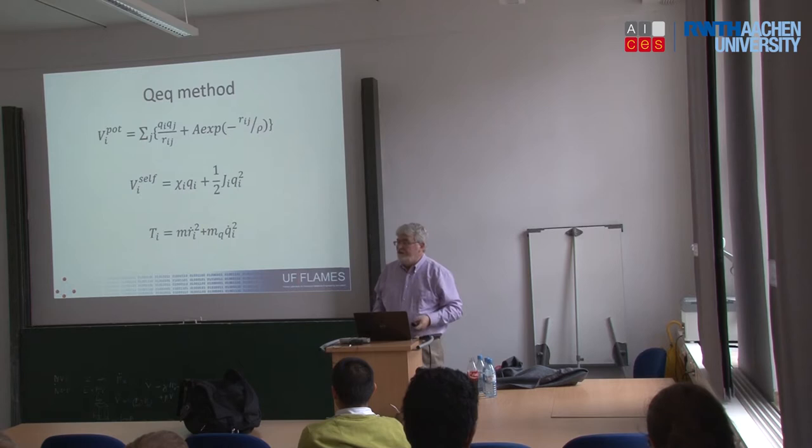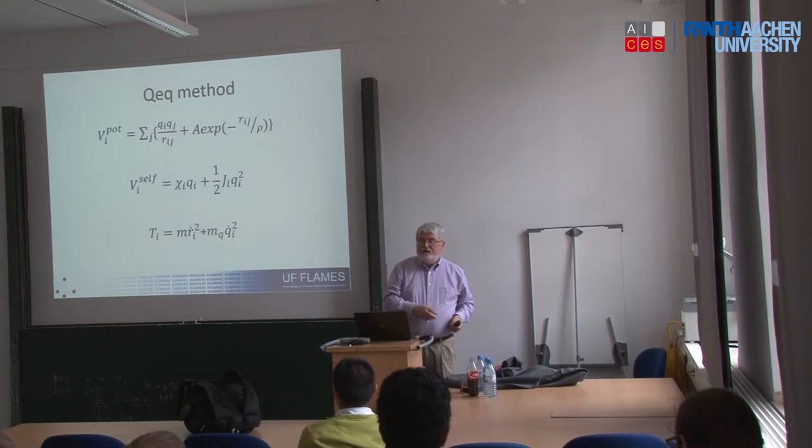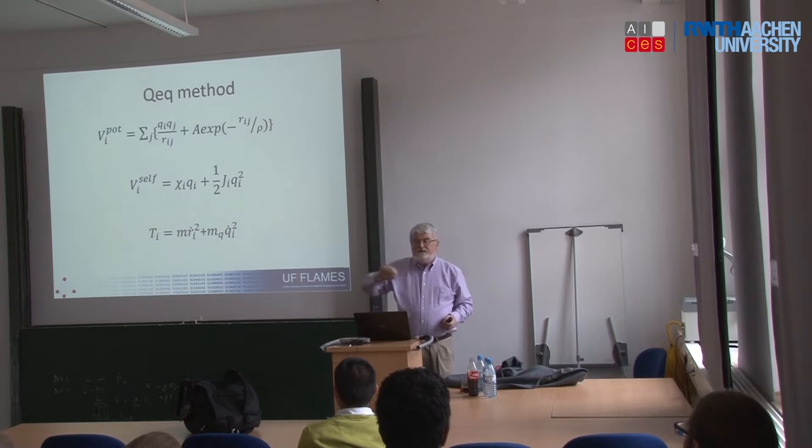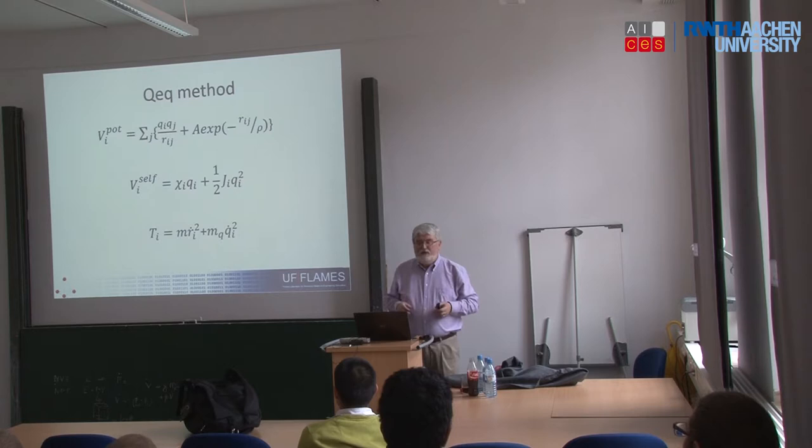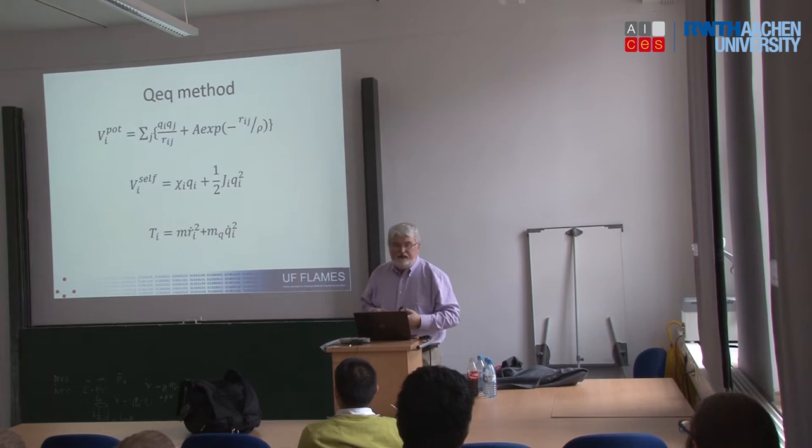So then we can go back to our old friend the Verlet algorithm, and we can write down an equation of motion. We can advance the positions as a function of time, and advance the charges as a function of time. Now we have a system where the charge on any atom can change autonomously in an algorithmic way. That's the basis behind it. Now, of course, there's ugly details in the implementation, but that's the basic process.